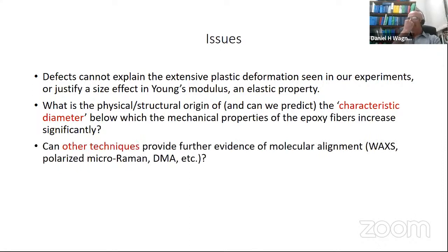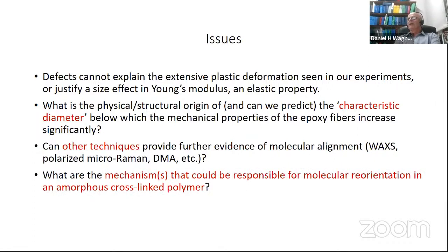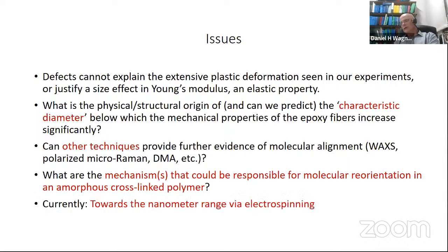Can other techniques provide further evidence of these alignments? We are doing right now polarized micro-Raman, DMA, and SNOM, which is an optical technique, which we are using to try to find evidence of molecular alignment, and what kind of mechanism can be responsible for this molecular reorientation in an amorphous cross-linked polymer. And what we are doing right now, which is very exciting, I have a student working full-time on this, a PhD student, is doing electrospun epoxy fibers.